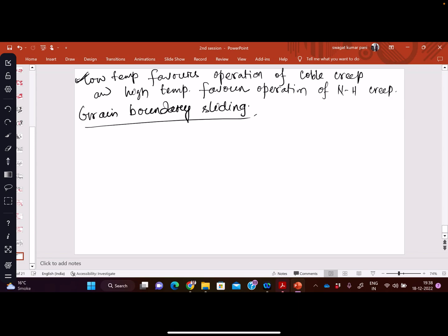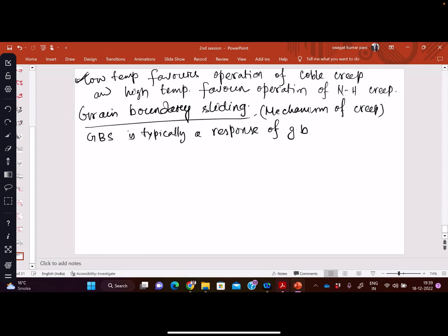So what is grain boundary sliding? This is also one mechanism of creep. This is typically a response of grain boundary, usually high angle grain boundary, to an applied shear stress. This is supposed to occur by the relative motion of grains along a common boundary or along a narrow zone adjacent to the grain boundary.